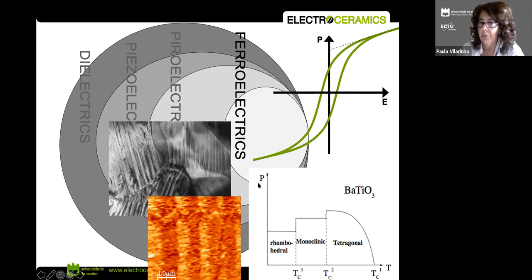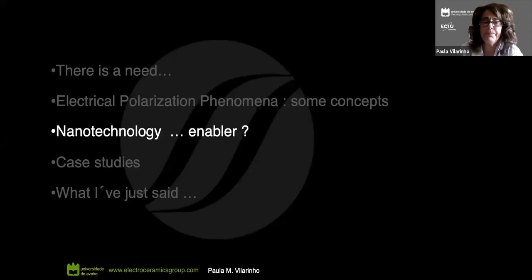And as you can see here, the polarization and the dielectric permittivity as a function of temperature show three main regions: a rhombohedral regime, a monoclinic regime, and a tetragonal regime. These are the structures that are really ruling the properties. And as we move down in temperature, the structure changes. This is very, very powerful in terms of the properties of materials. So a fingerprint of a ferroelectric is really what is represented here. That is the possibility of changing or inverting the polarization of a material. That's something that is relevant. We call these materials smart materials.